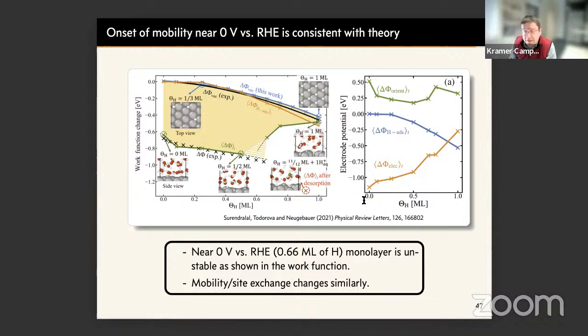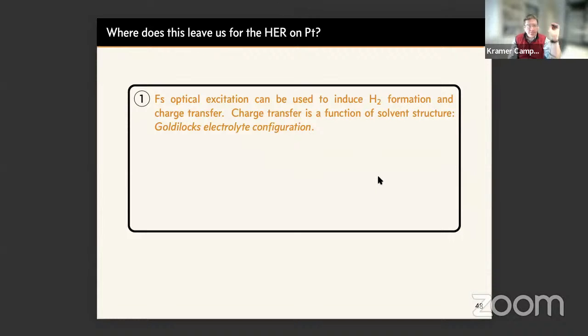They conclude in this paper that as one increases hydrogen coverage, one displaces chemisorbed water, and you lose the stabilization of the interface that chemisorbed water affords. And so this would suggest that the mobility and the site exchange of platinum should increase dramatically as one approaches this magic 0.6 monolayer on 111. This is in fact what they observe in simulations, and is consistent with this picture that I just told you. Okay, so this is really the end. Wow, it's great, it's right on time.